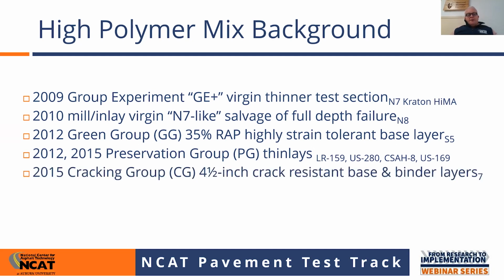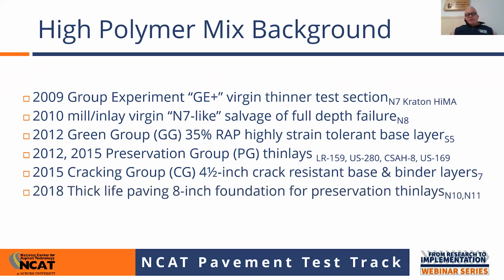All those were with HiMA binders, and then also in 2015 we built what we call the cracking group experiment. That was an experiment set up to essentially determine what laboratory cracking tests relate well to observed performance on the test track. In that experiment, we had thin pavements that would deflect a lot, but we were studying near surface cracking in the top 1.5 inches. So the bottom 4.5 inches was produced with HiMA binder to make sure that we would get those deflections that we wanted, but without bottom up fatigue cracking. And we had 7 layers that we built with HiMA binder in that experiment.